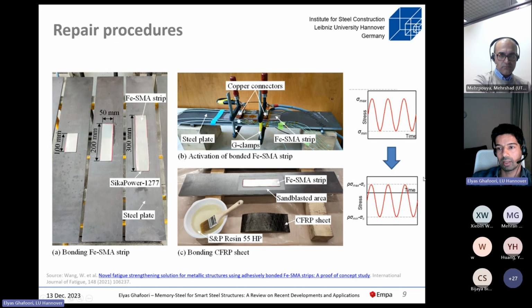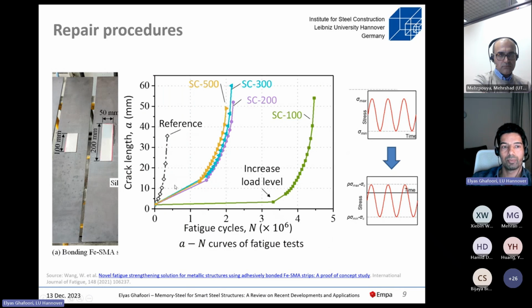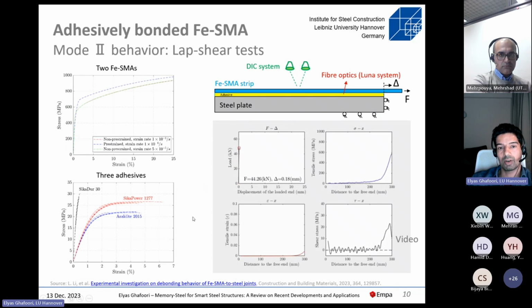There are different techniques we are trying right now, and by that we can of course decrease the amplitude of the stress along the steel plate, but also we can push the stress history from tension-compression to tension-tension at the critical detail near the crack. Under this patch, there is a crack. In that case, only the tension part is effective, from 0 to maximum tension, so we can reduce the stress amplitude. We did test, and we showed that by having such a system, we can arrest an existing crack.